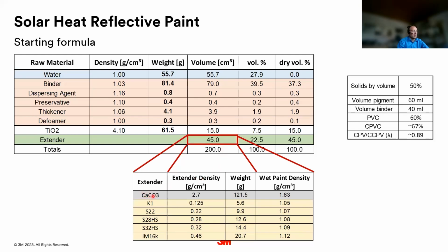And as a reference, we used calcium carbonate. And then we used different kinds of glass bubbles, always the same volume. But you can already see in terms of weight, it's a significant difference because of the lower density. And by the way, this also has a significant impact on the wet paint density, which is reduced here by approximately 30%. And so in the next step, we compare the performance of these different paints with respect to solar heat reflectivity.